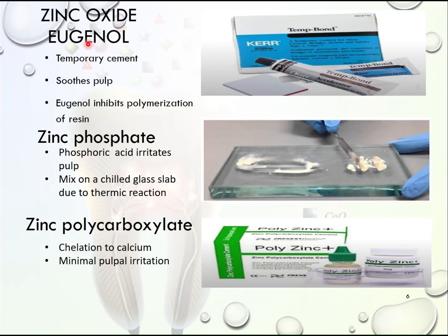Coming to zinc oxide eugenol, it is a temporary cement, it soothes the pulp, and it inhibits polymerization of resin. So after temporization, if you are replacing the temporary crown with a permanent crown, it is better to eliminate all the zinc oxide eugenol so that it will not inhibit the polymerization of the resin cement which you will be using for the cementation of the permanent crown. Because of these disadvantages, zinc phosphate came into role.